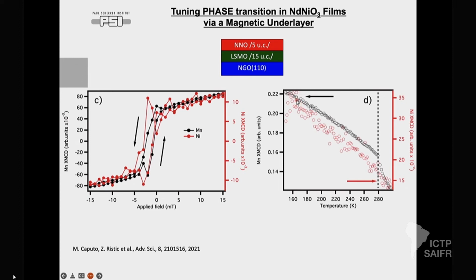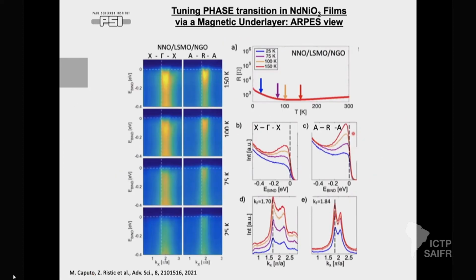If you look at how everything happens with temperature, this is the ferromagnetic moment of the LSMO, which shows the ferromagnetic-paramagnetic transition at 280. Interestingly, the ferromagnetic moment in nickel follows that line, showing the same trend. So that means they are locked together. Of course, magnetic ARPES is not easy, so we also look over the temperature range at the spectral weight. The quasi-particle stays all the time down to very low temperature, showing that the system remains metallic, as transport also says. So the system is metallic and ferromagnetic.